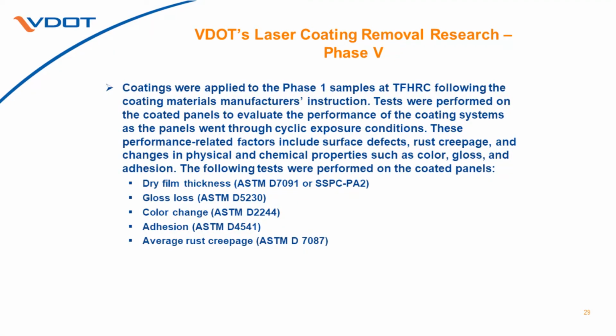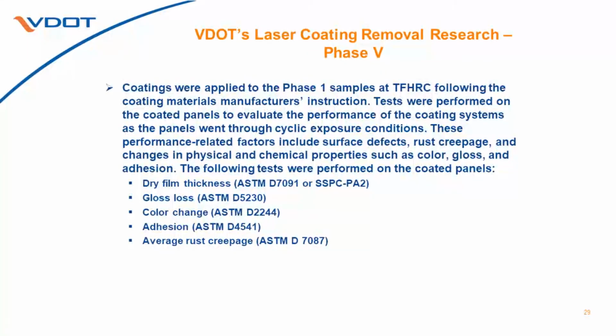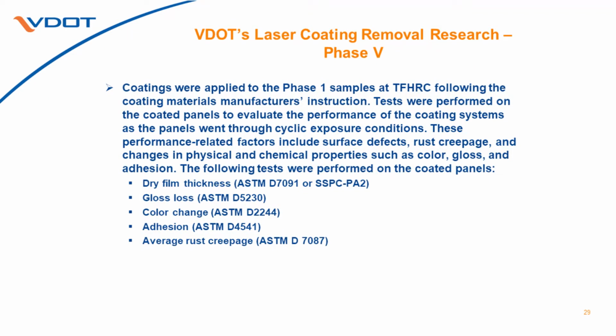Coatings were applied to these beams and tests were performed. The following tests were performed after the samples were coated with a coating that was provided by VDOT. Basically, it was an epoxy mastic coating, which doesn't typically require a surface profile. So we looked at the dry film thickness, gloss loss, color change, adhesion, and rust creepage.